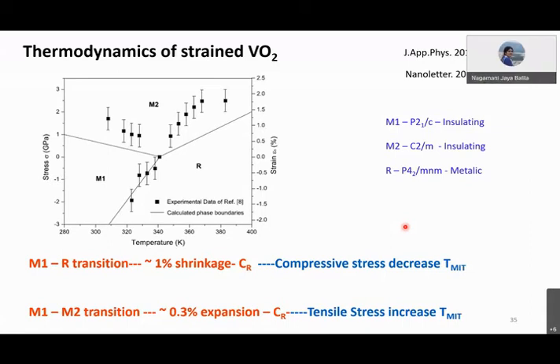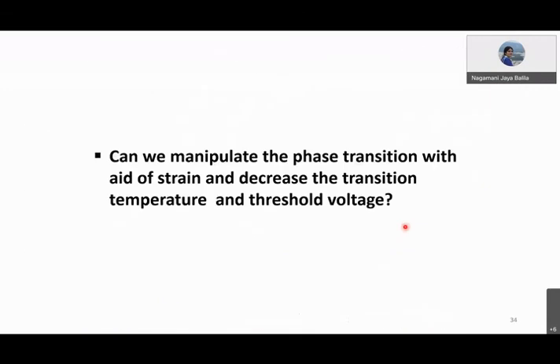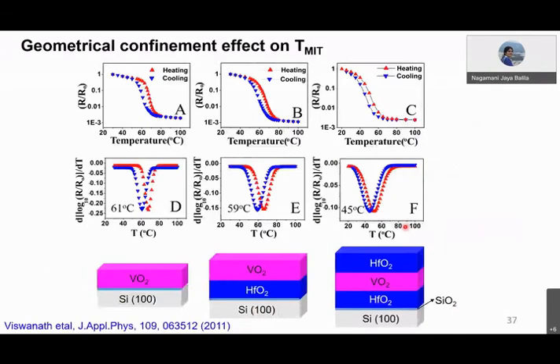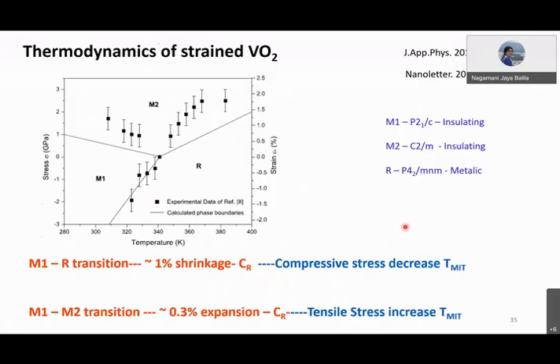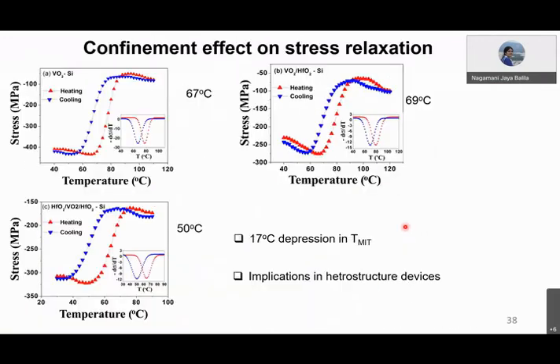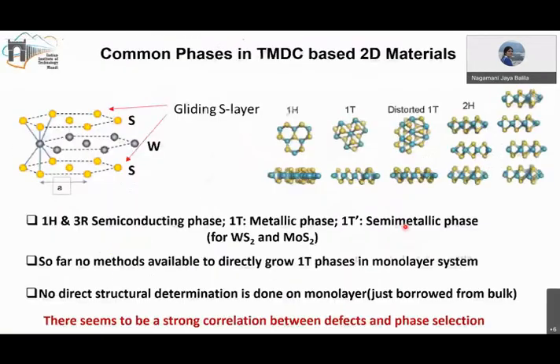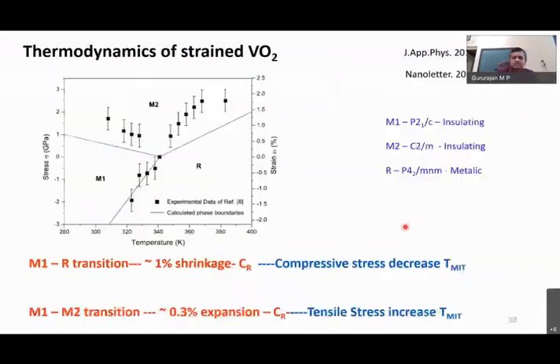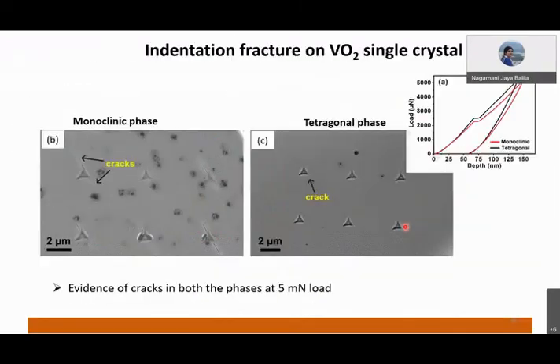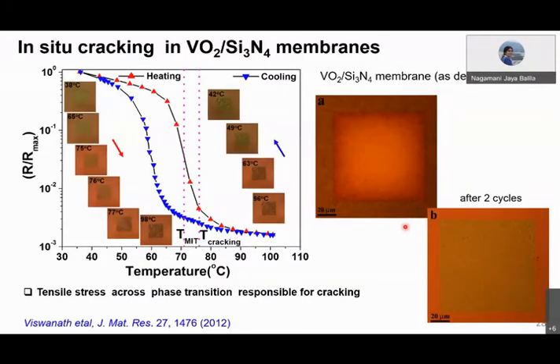Also, that slide showed that your film was cracking, right? So, is it cracking? Hello, can you hear me? Yeah, we can hear. Sorry, the membrane one was cracking, right? So the cracking stress is sort of lower than the twinning stress here. Is that why it didn't accommodate?